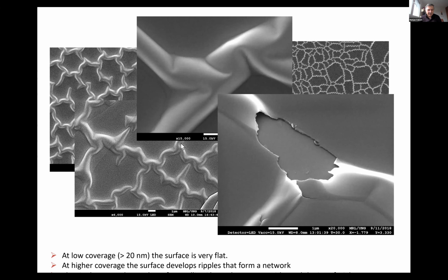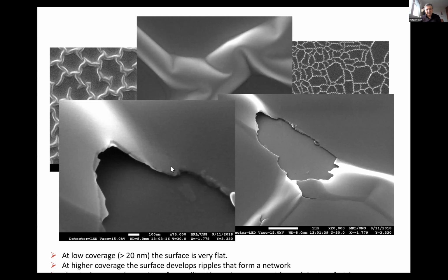And why do they appear? Actually, it's quite like in a dry apple. We have quite a rigid layer of rigid substrate, bismuth selenide. On the top of it, we have a soft metallic bismuth layer, and on the top of that, we have again a rigid titanium selenide layer. And when that is growing, the tension on the interfaces becomes too much, and these ripples start appearing. It's like in the dry apple.